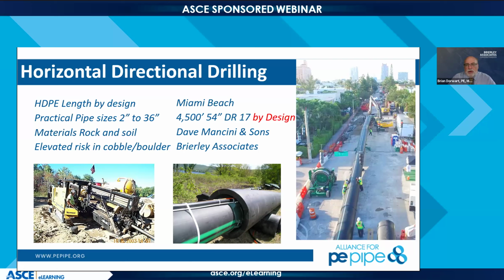Well, the issue on this one, I'll just take the lead on the Miami Beach because it was my project. Very interesting project, 54-inch. We had to use DR11 and DR17. We mixed it up. Because there was very limited availability of pipe, we put the lower DR at the bottom, lowest part of the bore, and then we used the DR17 on the ends of the bore, just sort of as a way to use what you got. The important part of this, we're putting in 3,000 foot sections here.